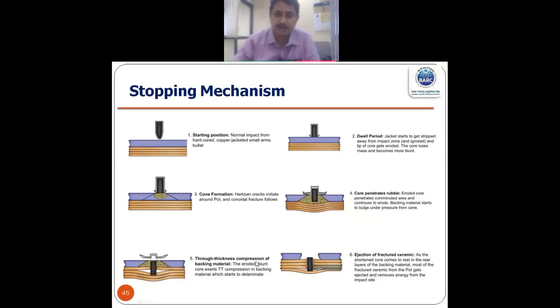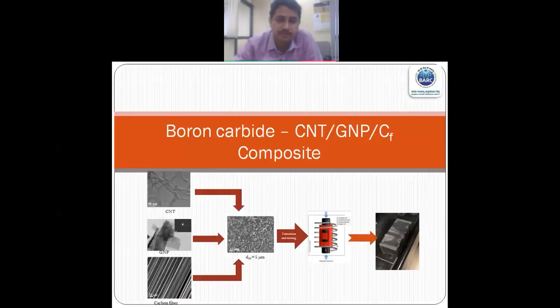And in case of hard armor panel, when we talk about hard armor and soft armor together, what happens, the bullet comes, it hits the ceramic and it will make the face blunt and a cone shaped fracture will happen, and the bullet jacket is kept outside, but the core travels inside, and this core is finally entrapped into the backing material. So by this mechanism, the bullet is stopped.